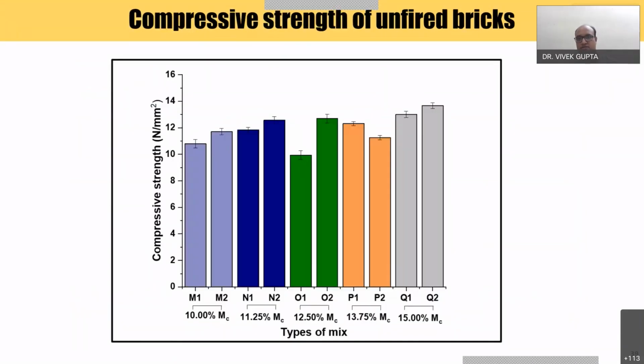So these are the compressive strength results, where we found that the mixing sequence 2 is effective for the better performance of the unfired bricks. And with the increase in the moisture content, there is an increase in the compressive strength in general. And for the Q2 mix, we have observed the highest compressive strength.